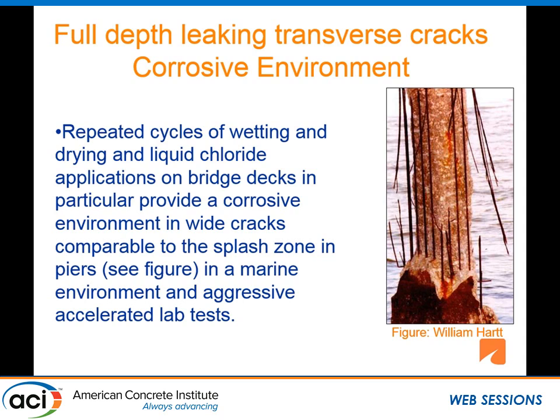But if you think about a crack in a bridge deck, it's just as similar: wetting and drying, salting after salting, as well as flexural movements because of the tractor trailers driving over the bridge. Also, we have some very aggressive lab tests that in many cases really don't give you an accurate prediction of service life because they're so harsh. But I believe in the situation of cracks in decks, many of these very aggressive tests do provide an accurate prediction.